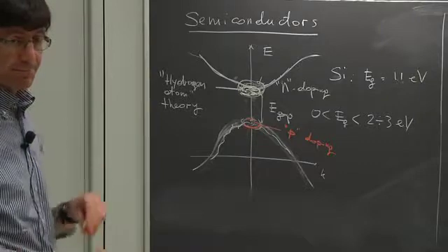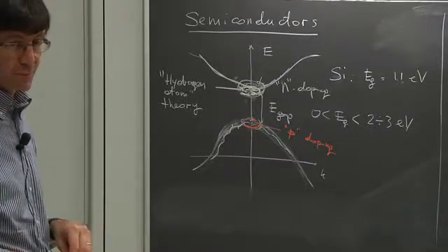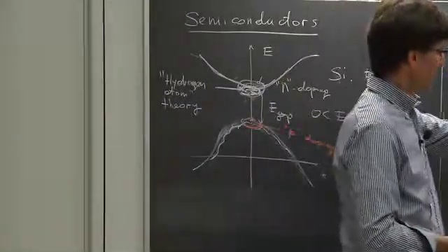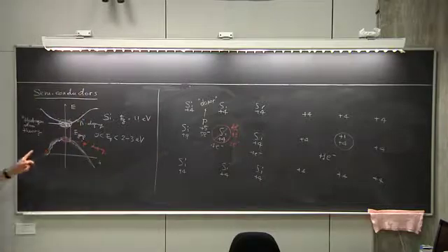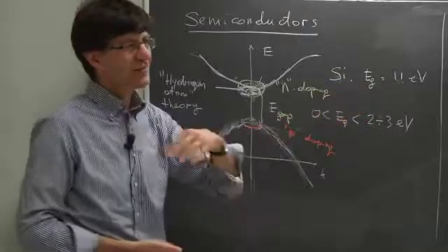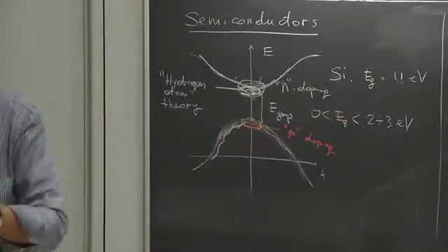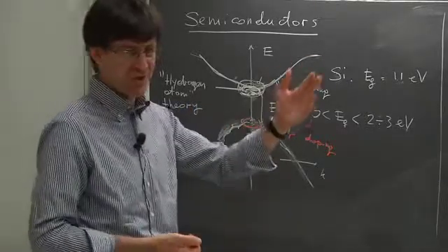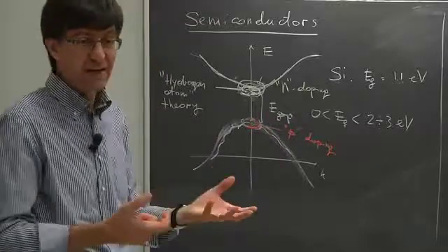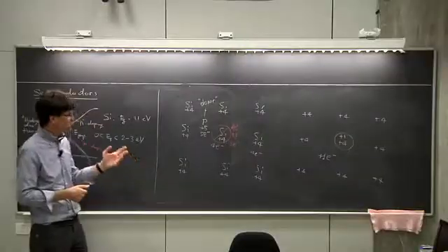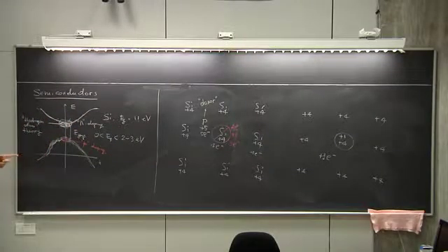Sorry? Yep. Which one is more efficient, doping or thermal excitation? Oh, clearly you can reach concentrations which are much larger using doping. There are two consequences of doping. First, you can introduce in principle an arbitrarily large amount of impurities. Of course, after a while, the impurities will start to cluster, will start to form complexes, so you lose all the nice properties. So you cannot exceed a given threshold of concentration of impurities. You have a solubility limit. But as long as you're below the solubility limit, the amount of carriers that you can generate with this kind of chemical doping is typically much higher than the one you induce with temperature.